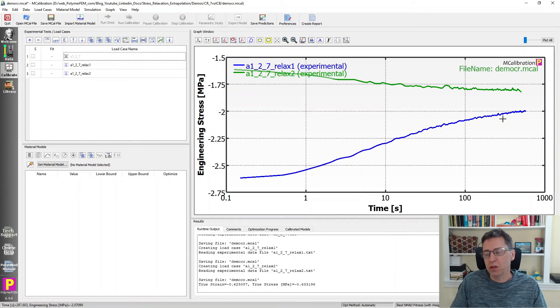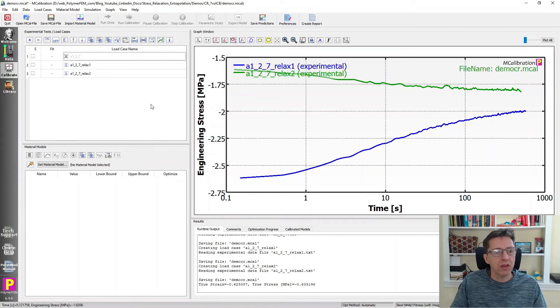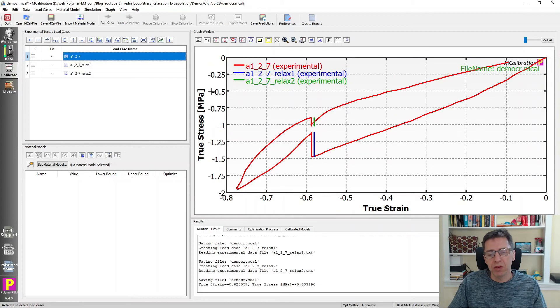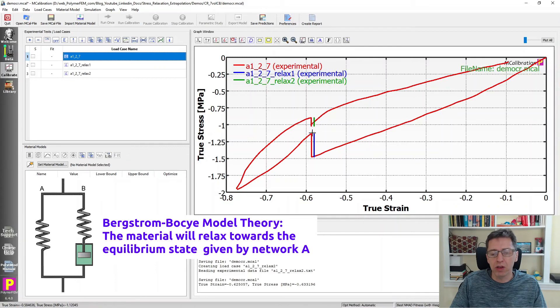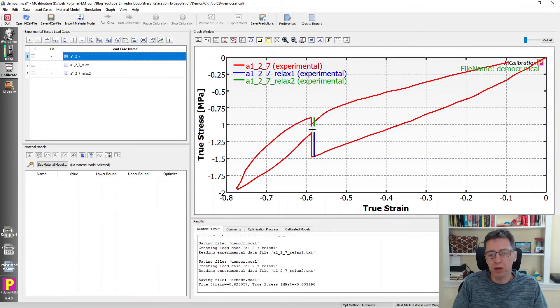But this is clearly much easier to extrapolate — say, 2,000 or 5,000 seconds — when plotted this way. Looking again at true stress versus true strain, we can see that as you compress it, the stress relaxes if you hold the strain constant. Then as you continue to compress, stress goes up, and as you unload it goes down. As you hold the strain constant during unloading, the stress increases, and this point keeps moving closer to the other. There is an equilibrium state the material is trying to reach for many elastomers.